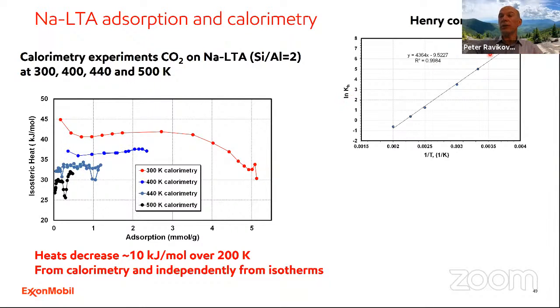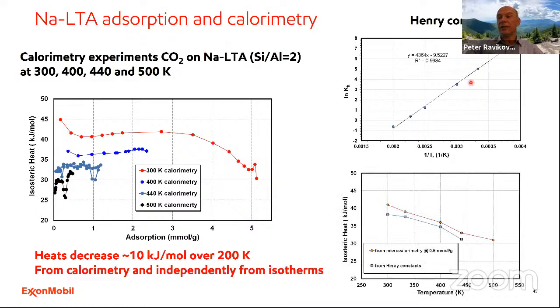And as you plot the logarithm of the Henry constant as a function of inverse temperature, you are not getting exactly a straight line. And if you calculate the heats of adsorption from just adjacent temperatures, you actually see quite substantial, very substantial temperature dependence, which is in agreement with the calorimetric measurements. Again, experimentally, we checked that we have consistency between the calorimetric and adsorption measurements.